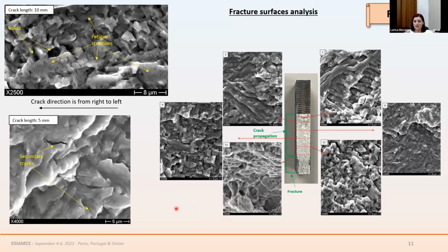So also in this case, particular influence of the recycling strategy was not observed. And I also wanted to highlight that there was a transition from this fracture mode, which is more ductile in this area, closer to the first steps of the crack propagation stage, while